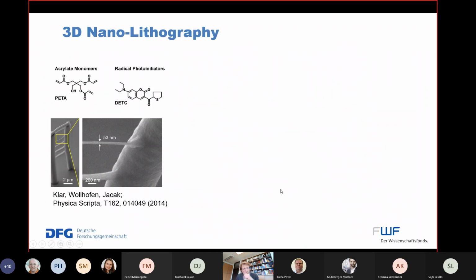And it actually works. I show you here some of our own examples. This is a door frame, and the door frame, freestanding in 3 dimensions, is written by 2-photon lithography. Then we switch on the STED beam, and we write these bars here. From bottom to top, we increase the STED intensity. And you see that in 3 dimensions, using visible light, we get a bar that has a lateral and axial dimension of 53 nanometers. That is lambda over 10.